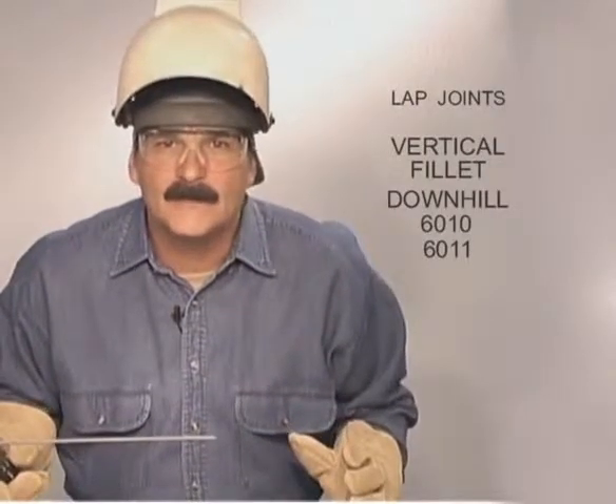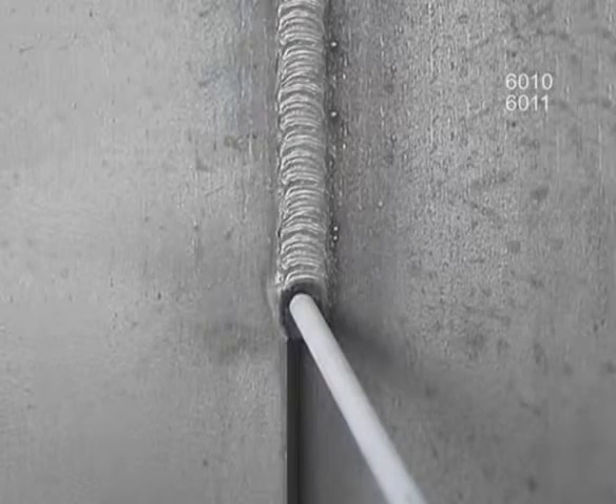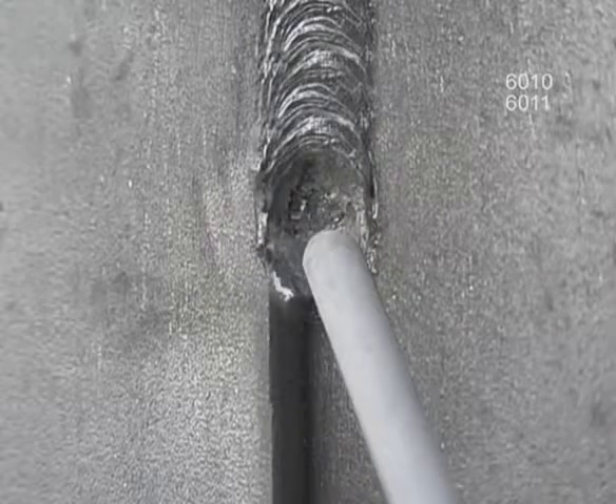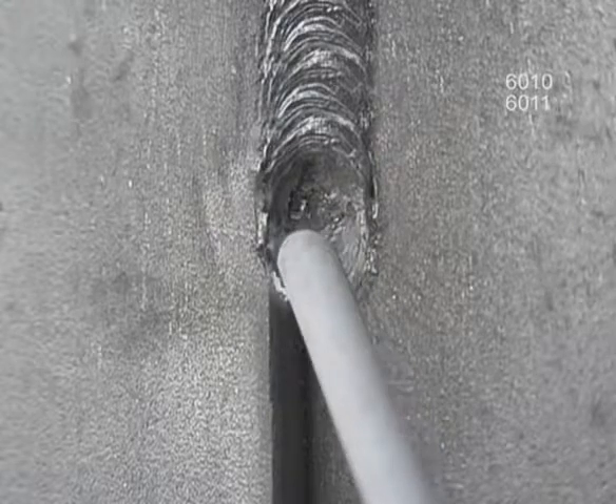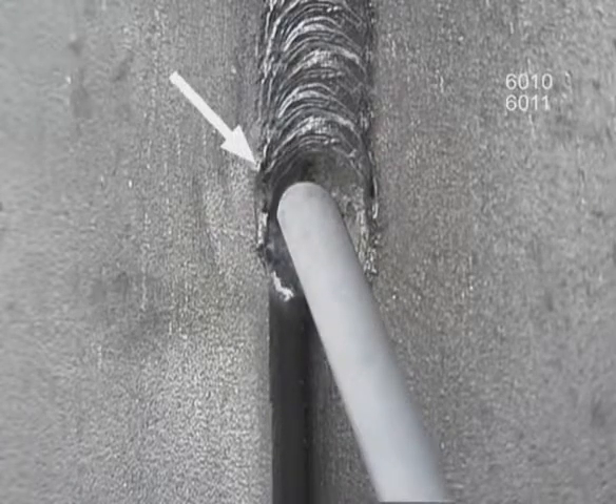On vertical lap joints, the outside corner is going to heat up a lot quicker than the surface. For vertical down welds, angle the rod up slightly. Carry the heat on the back piece. Move into the corner, pushing the puddle to the edge, then back out. Adjust the travel speed to stay ahead of the puddle and make sure you're on the leading edge of the puddle to move into the corner.